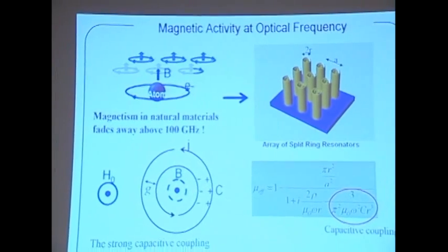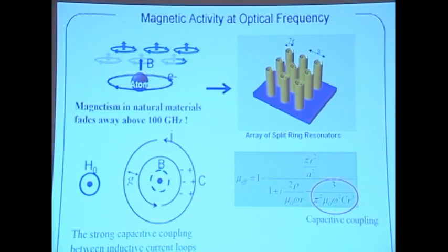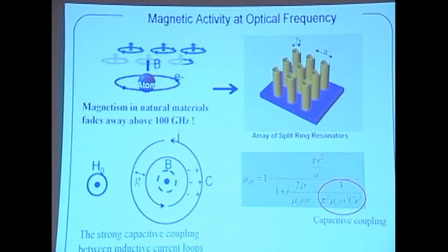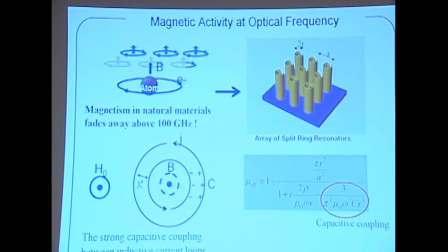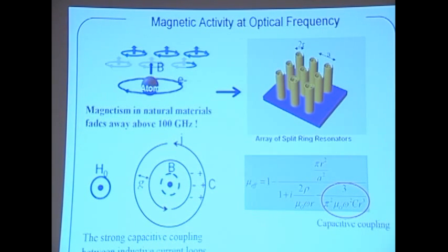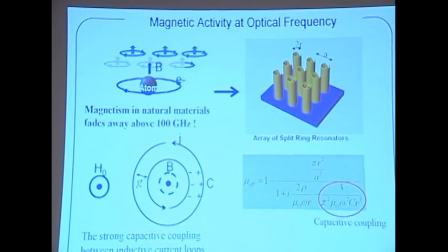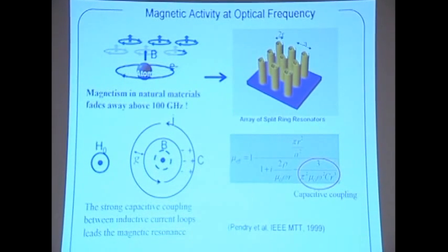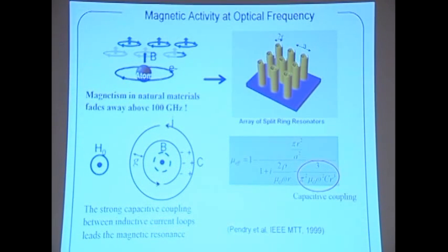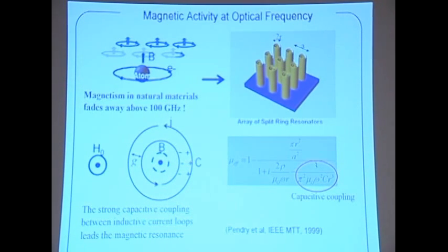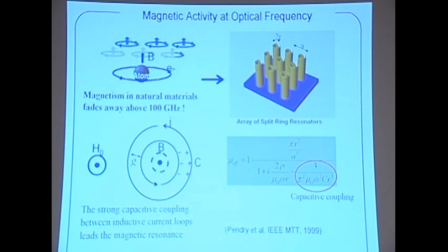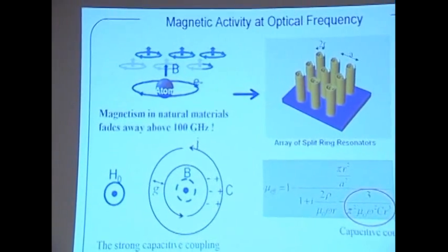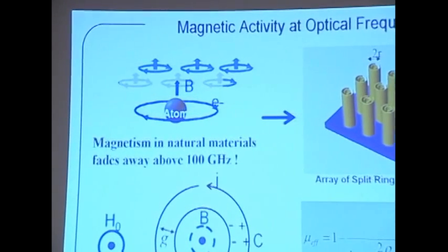Now, why is that? Because in natural materials, as we know from college physics, the electrical response of the materials is based on monopoles, the electron charge moving around. Magnetism, however, so far is based on dipoles. And people are still searching for magnetic monopoles. So all the natural magnetic materials we have found are based on dipoles. Those dipoles form a magnetic domain, and the response is the domain response. By the nature of dipole response, that is much slower than monopole response. That gives all natural materials a magnetic response up to about 100 gigahertz. Above that, all the magnetic response fades away.